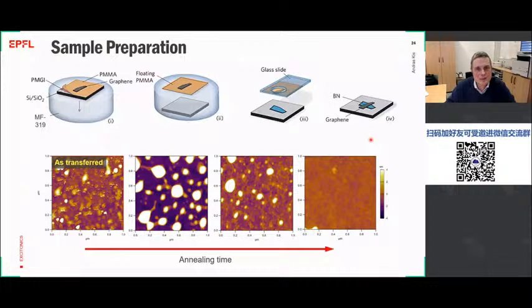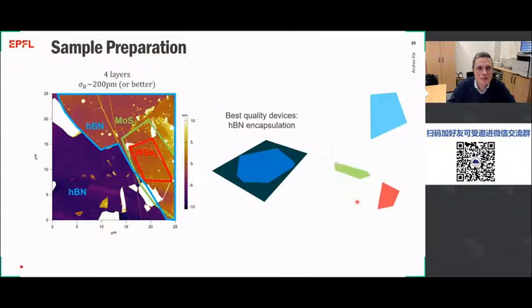Now, what is important for seeing these interlayer excitons is that you need to make very nice, very clean, high quality heterostructures, and it's important to anneal them properly so that once you start off with something relatively dirty with a lot of residue, you can end up with a clean interface in the end. And then when you make your final heterostructure, which for the highest optical quality has to be also encapsulated in boron nitride, there are all these annealing and different cleaning procedures and a lot of practice. You can end up with these very, very clean interfaces where you can actually observe the interlayer excitons.